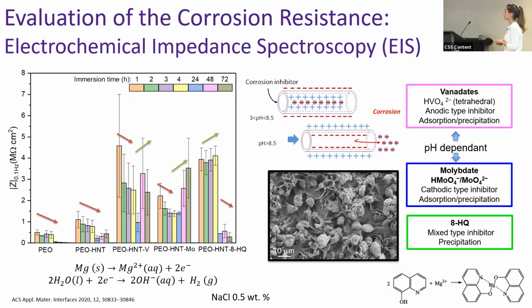So according to the bibliography, vanadates are anodic inhibitors, molybdates are cathodic inhibitors, and hydroxyquinoline is a mixed type of inhibitor. And the corrosion inhibition mechanism is probably associated with a mixture of adsorption and precipitation reactions that result in the formation of complexes that precipitate on top of my anodic and cathodic sites, isolating my substrate from the environment. However, we would need to do further experiments to figure out what the specific mechanism is in these coatings.